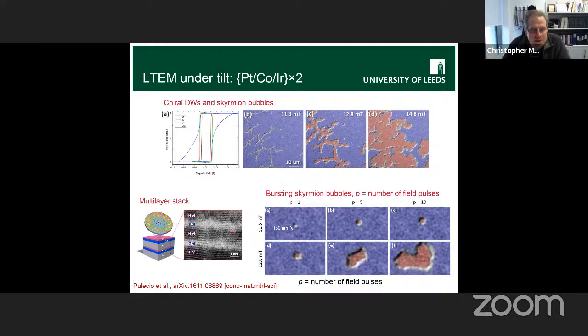These lines in the image that you can see are the planes of atoms within the multi-layer. They're the lattice fringes. So you can see there's about 3 or 4 planes of atoms thick. And so their properties are totally dominated by the interfaces. So they're magnetized out of plane because you get an anisotropy from these interfaces. That's what these polar Kerr loops show us. But they also have quite a strong DMI because of these dissimilar metals, platinum and iridium, above and below them.